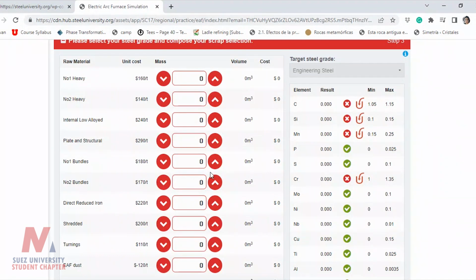If you add scrap classified as plate and structural, and you use all the 80 tons for these materials, you will see that you have to add carbon, you have to reduce the silicon, you have to reduce the manganese, the phosphorus, and you have to add chromium.